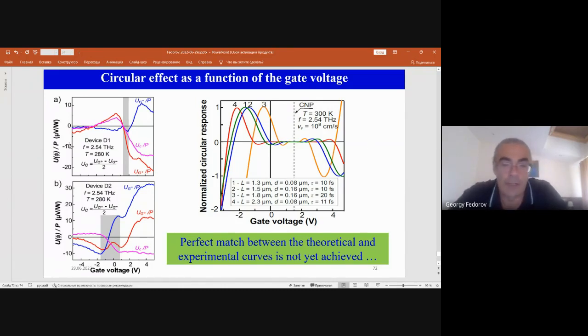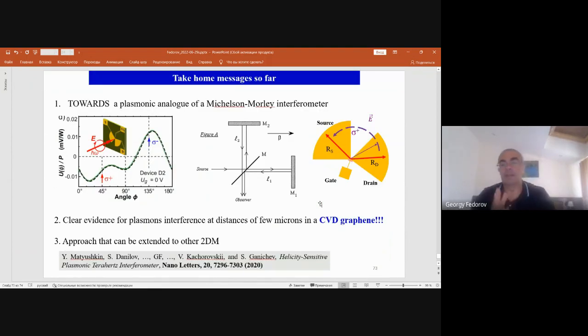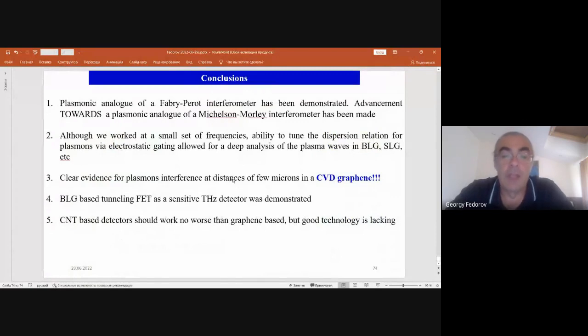But otherwise, we demonstrated that the plasmon interference in the channel does contribute to the photoresponse. And by this, we prove that just graphene with two contacts may operate as a Michelson-Morley interferometer. And with this, I come to the main conclusions of my talk. So we demonstrated a Fabry-Perot interferometer made with high mobility graphene, and it can further be exploited as an on-chip spectrometer for many different applications. And it also can be used to restore the single particle spectrum of the material that you work with. I didn't talk about this much, nevertheless, just believe me.